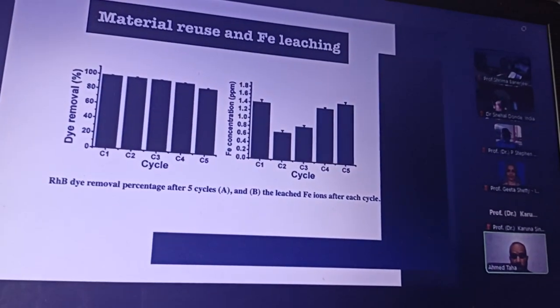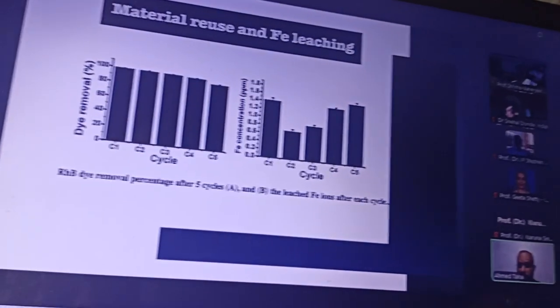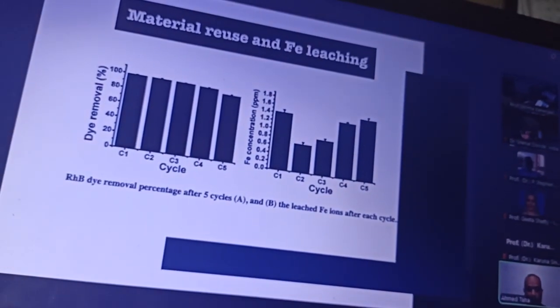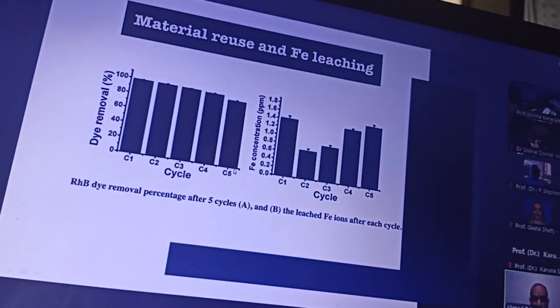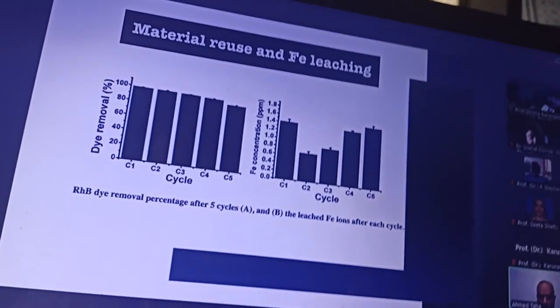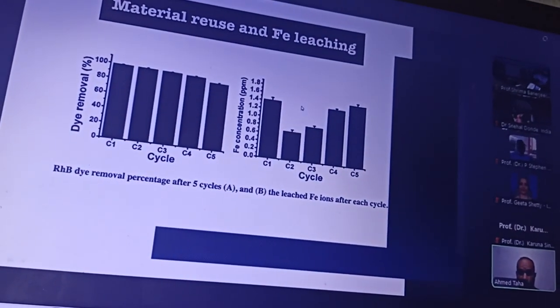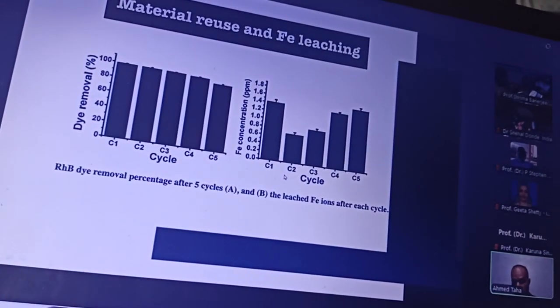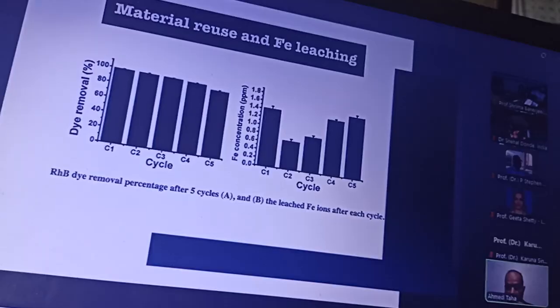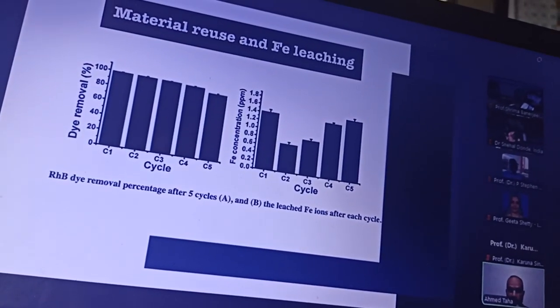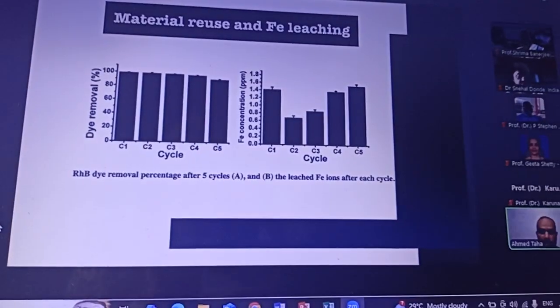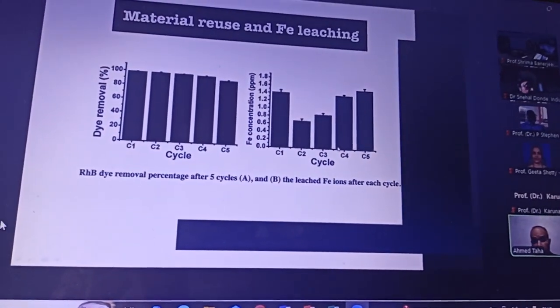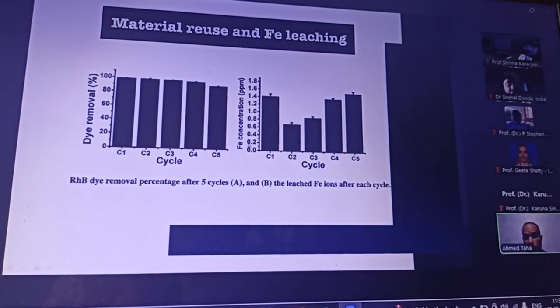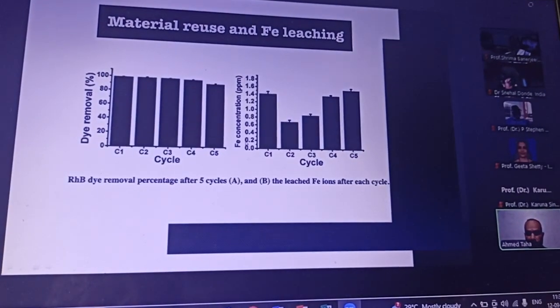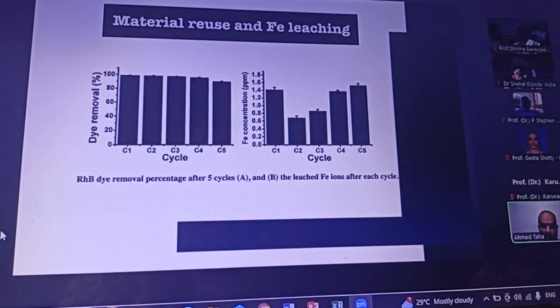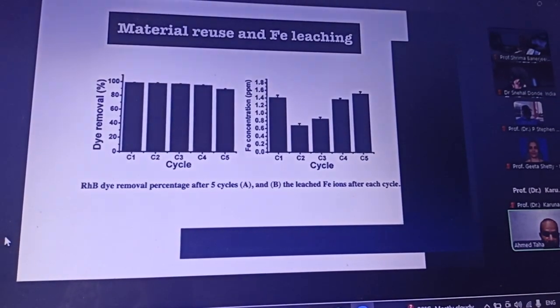One important measurement is to study the recyclability. As we mentioned, in traditional Fenton we cannot reuse the catalyst, but here we actually can. So this is 5 cycles of collecting the catalyst and reusing it again, and the performance is still good. We studied the leaching of iron also during the reaction, because our material has iron, and this is a very strong reaction. It can cause leaching of some of this iron into the solution. Actually, we found there is some leaching of iron, which was actually good for the reaction. It still can help in improving the performance, as I will explain later.